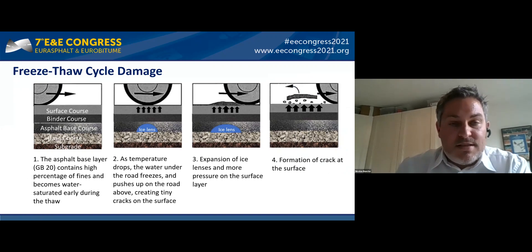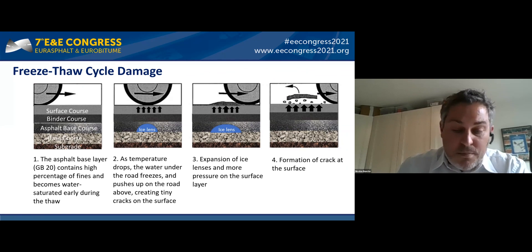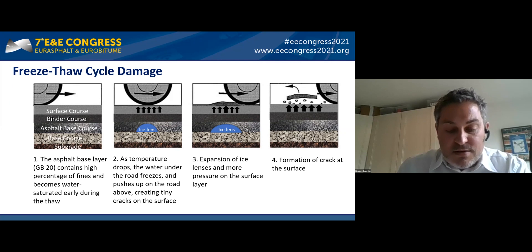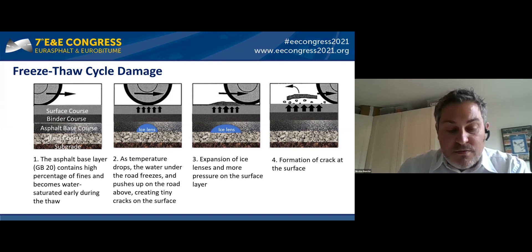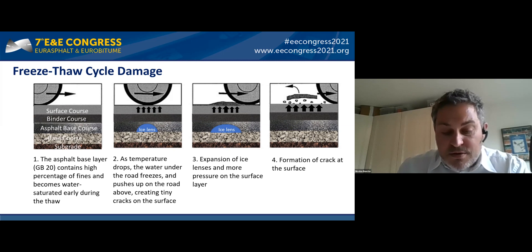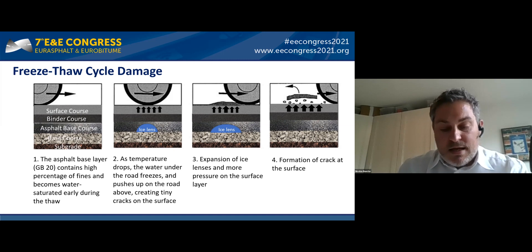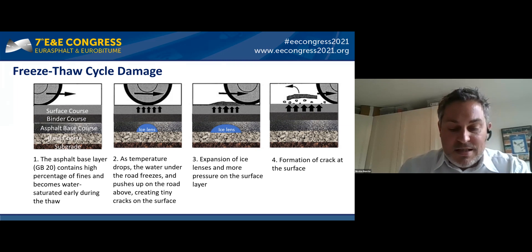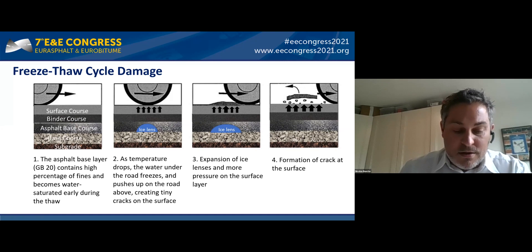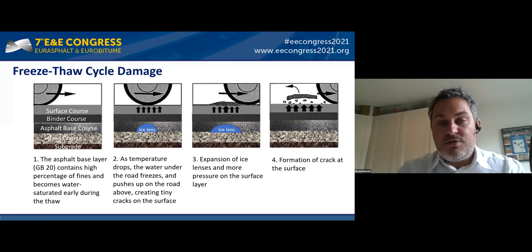The freeze-thaw cycle mechanism is defined as water penetration inside the asphalt pores accompanied by the variation of positive and negative environmental temperature. Damage induced by freeze-thaw cycles is caused by water changing into ice, leading to expansion of water volume and loss of adhesion between asphalt and adjacent aggregates. After a large number of freeze-thaw cycles, stress decreases the material tensile strength and causes micro-damage on the surface, which accumulates and deteriorates the asphalt-aggregate bond, allowing water to enter and increasing aggregate stripping.